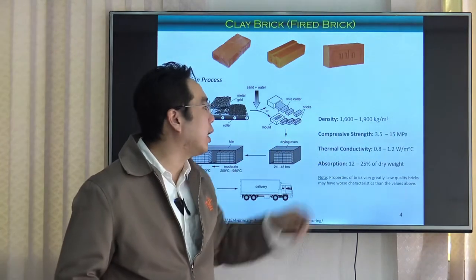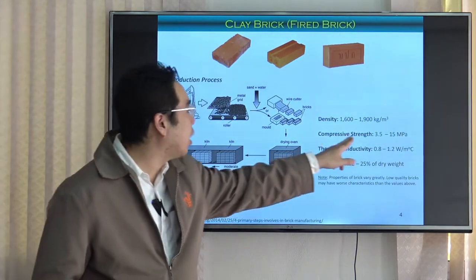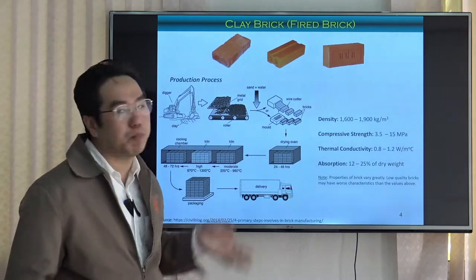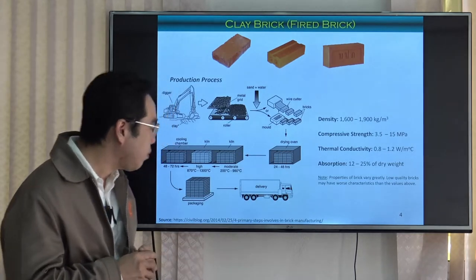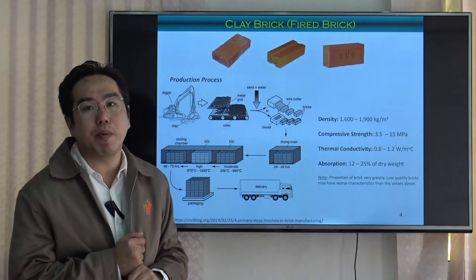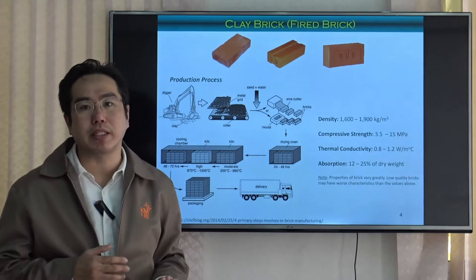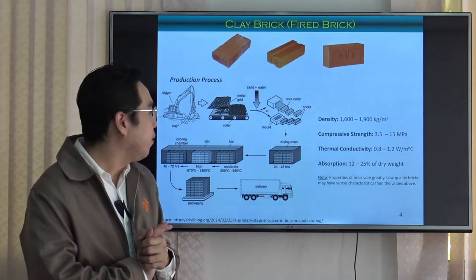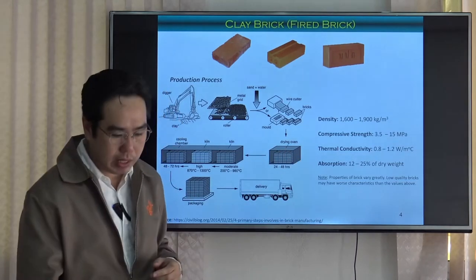The compressive strength of the clay brick is normally lower than normal concrete, and the variation of compressive strength is very high — so if you want to use this brick to resist load, you must be aware of this. The water absorption of this brick is quite high; it has been reported that this type of brick can absorb from 10 to 25 percent of its own weight. That value is quite high for a construction material. It also has considerable thermal conductivity.